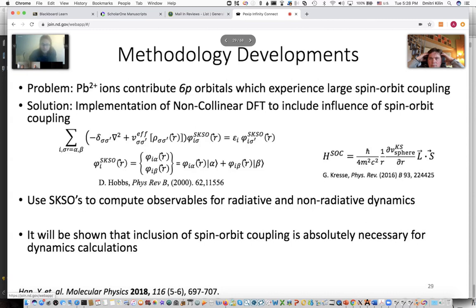So our solution to this problem is to implement non-collinear DFT, which allows for the description of spin orbit coupling. So it allows eigenstates which have spin up and down contributions. And that's described by the spinor Kohn-Sham orbital, where it has contributions from alpha, spin up electrons, and then beta, spin down electrons. And then the energies are corrected using this spin orbit coupling Hamiltonian, which is implemented into the software. And so some of this work was already worked on previously by Dr. Han in a paper, I think, for their dynamics.